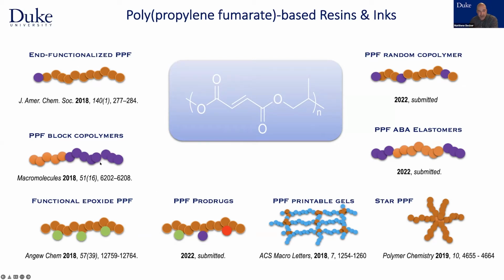And just to give you a little frame of reference here without going into too much detail, this is the base structure of this material. Its degradation products are fumaric acid and propylene glycol. And the purple units here are the ones that are actually cross-linked to form the solid network from the oligomeric resin. And we've done a lot with end-functionalized materials where we're tethering growth factors. We've done some prodrugs. We've done a lot with gels.